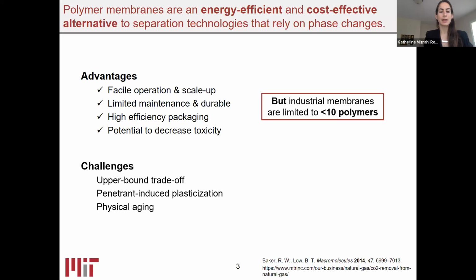The second is penetrant-induced plasticization or swelling of the polymeric material upon exposure to a polarizable gas at high pressure, such as CO2. And finally, physical aging or the densification of the membrane over time, which can change its performance and therefore render it unusable for industrial applications.